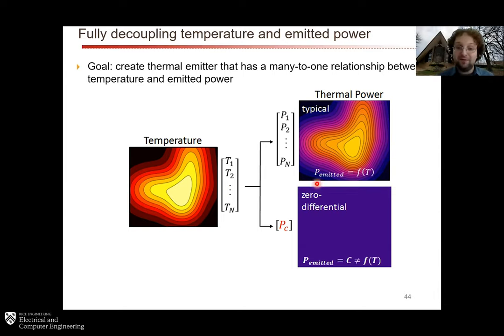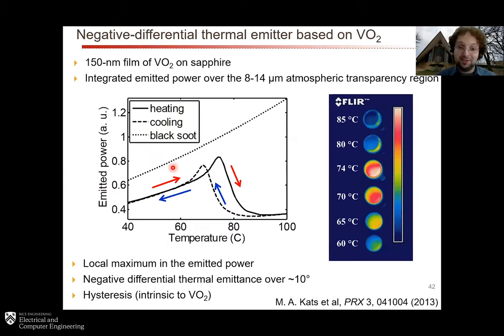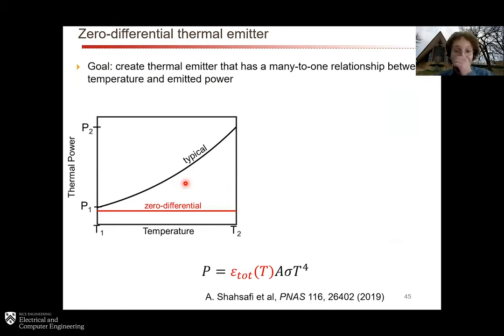In other words, you have a zero differential emitter, because the derivative, essentially the slope of this curve, is going to be zero. So here's a visual representation of this. This is the thermal power versus temperature for a typical thermal emitter and then the zero differential emitter. And the only way that this can happen, if you look at, for example, the Stefan-Boltzmann law, is if the emissivity, which can be a function of temperature, decreases to exactly cancel out the T to the fourth increase. And in that case, you have this zero differential effect.